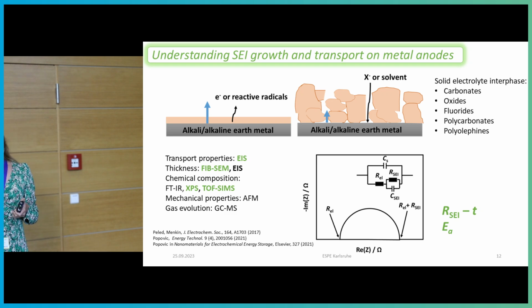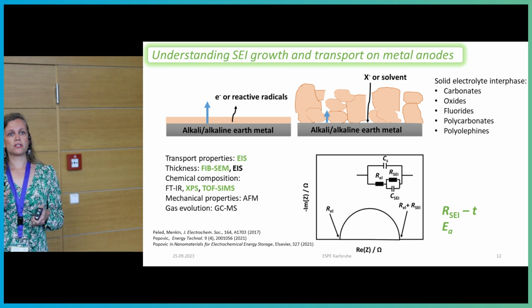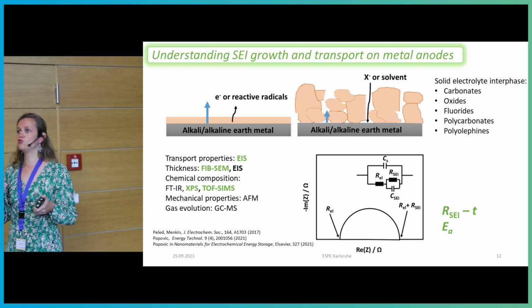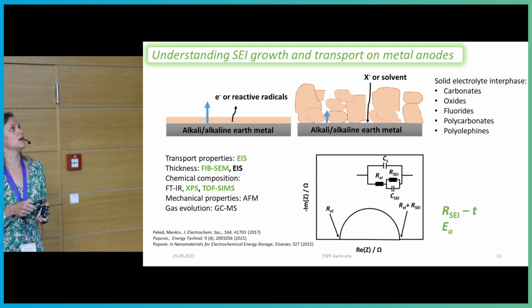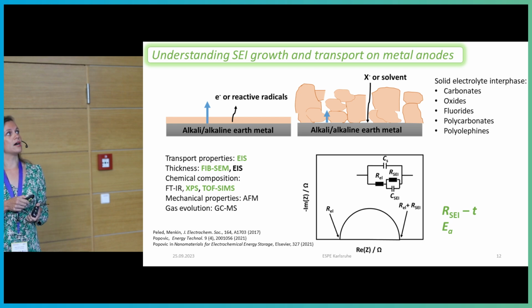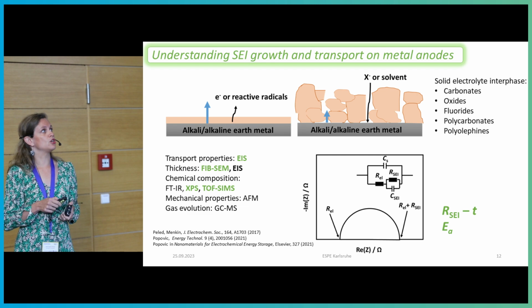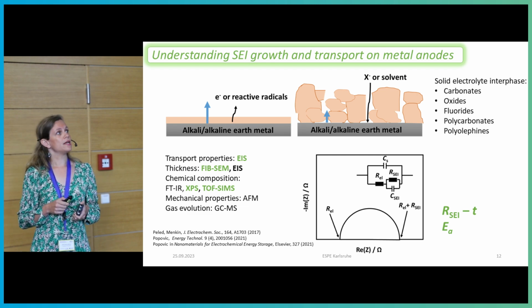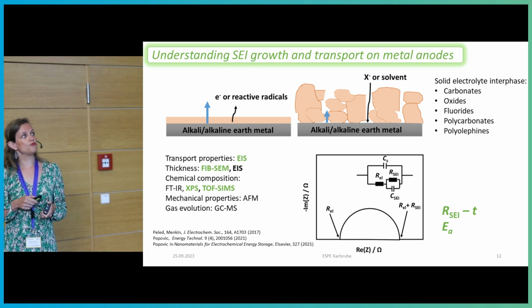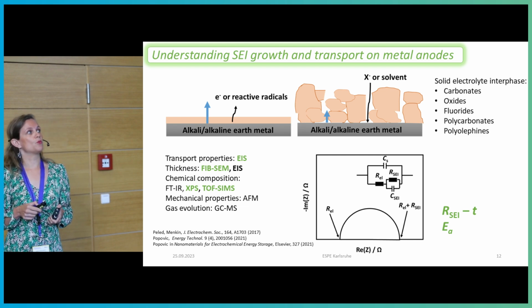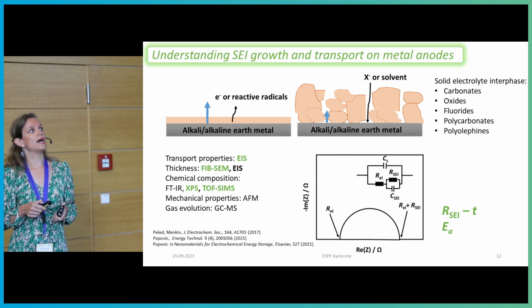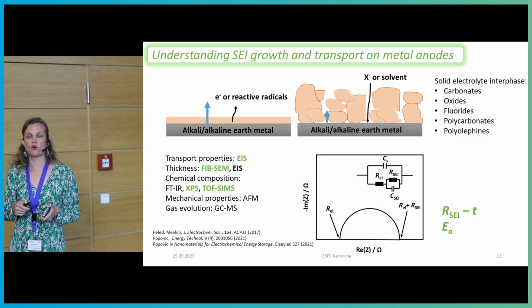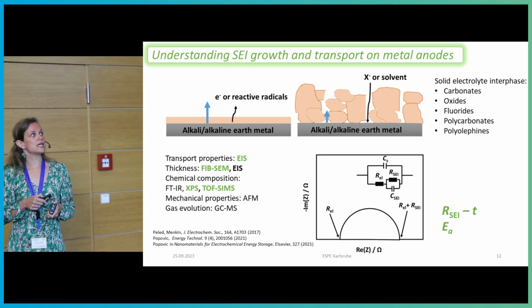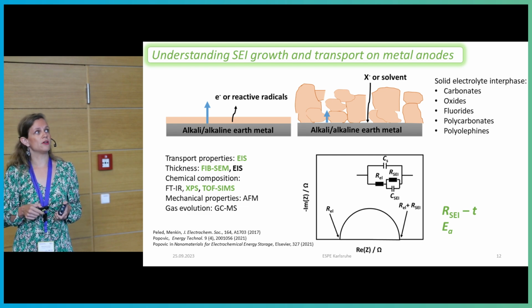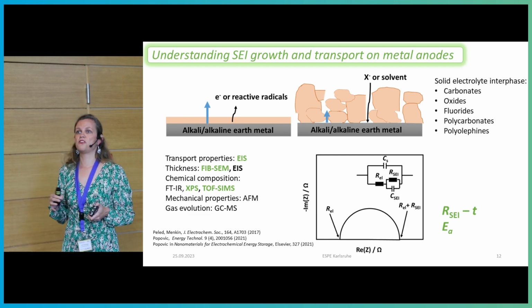So what I was thinking about quite a lot in the last years is how the SEI actually grows on metal anodes. And in that sense, I can imagine two different mechanisms. One is that we start with an alkali or alkaline earth metal, and then we form a certain initial film that is either electronically conductive or contains reactive radicals. And then this film grows from the solid-solid interface above. The other way that we can imagine the growth is that the initial film that is formed is porous. That means that when we have this porous film in contact with the liquid electrolyte, either the solvent or the anion can diffuse through its pores and then again react at the liquid-solid interface. Of course, SEI is shown here as one material, but it's a very complex material consisting of many, many different phases. So it's very hard to deal with.